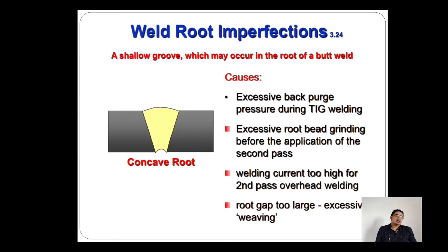The second main reason is excessive root bead grinding before the application of the second pass. Once our welder does excessive root bead grinding before the second pass, this may happen. The third one is welding current too high for second pass overhead welding. When the welder is performing overhead welding and the current is too high, what will happen? The first layer of the welding may, due to gravity, melt and go down. So you can find such a discontinuity.